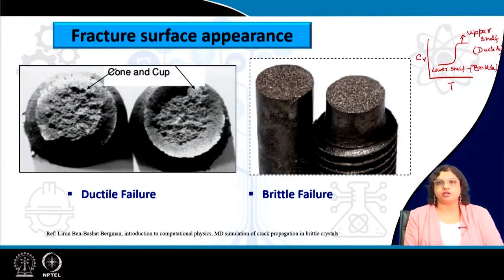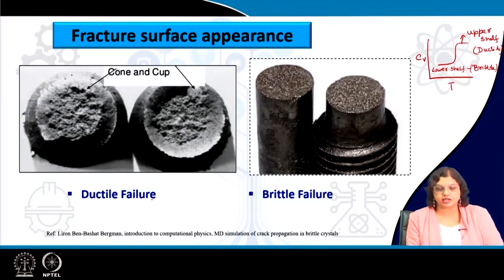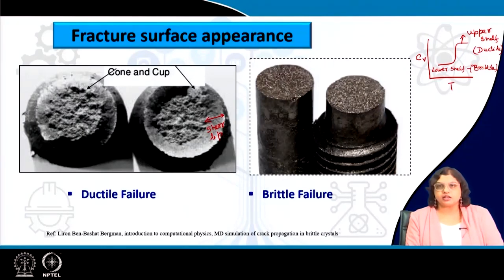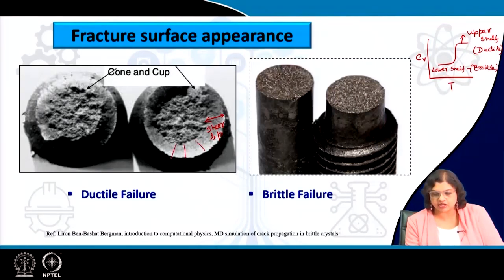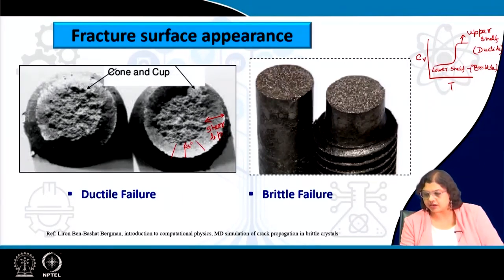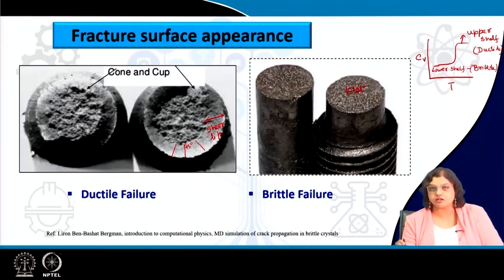This is apparent from the fracture surface itself. The difference between ductile and brittle failure: in the ductile case we see a significant amount of shear lip. For a Charpy test we use a rectangular notched specimen, and there will be significant deformation reflected as a shear lip near the edges — a 45-degree deviation with respect to the loading direction. For brittle failure, seen at the lower shelf, we see a perfectly flat fracture surface, signifying brittle fracture.